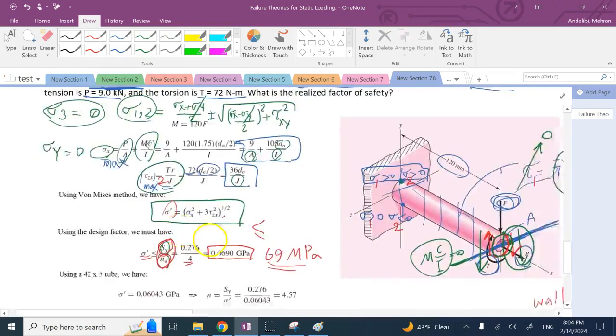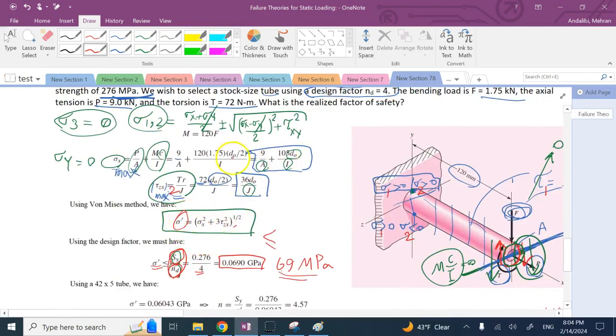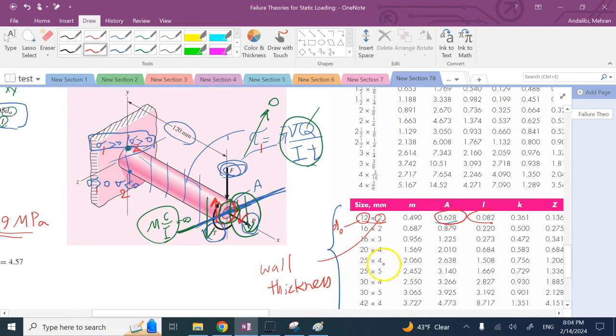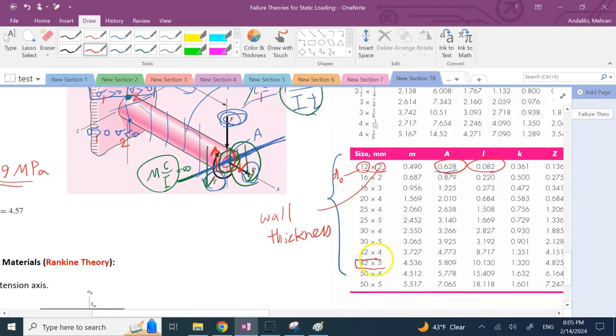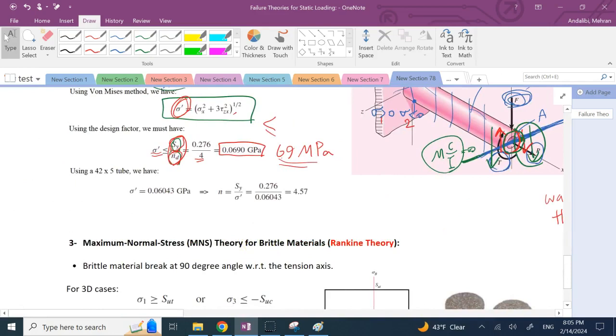If I plug these numbers in, I'll get what? I get a value for sigma x and tau xz, and as a result, I get a value for sigma prime. And then I can check whether that sigma prime is less than 69 megapascal or not. And if we go down this list, all of these tubes from the top would fail. Their stresses would be more than 69 until we get to this guy. Right when we get to this, your maximum sigma drops below 69 megapascal, and so a 42 by 5, if we use that tube, your maximum stress will be 60 megapascal.